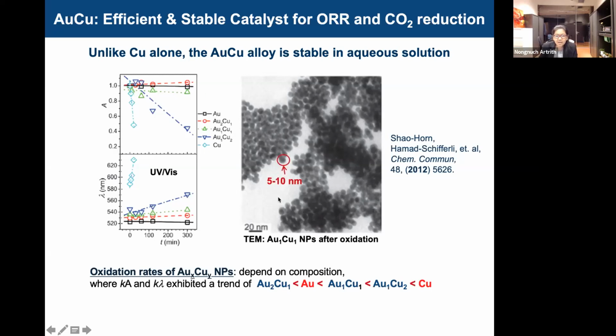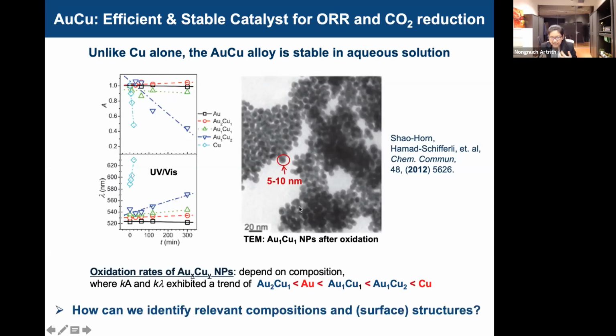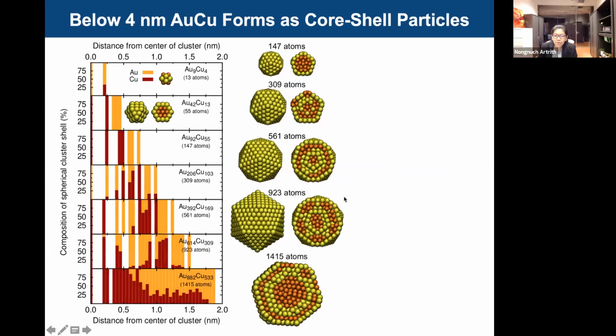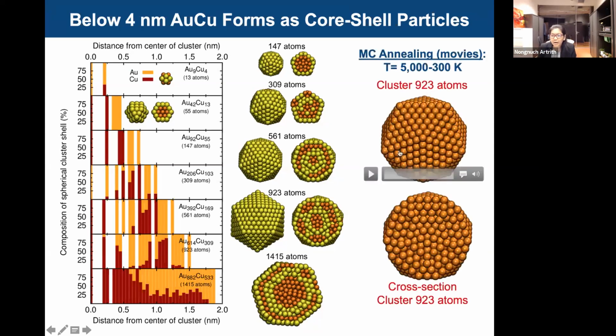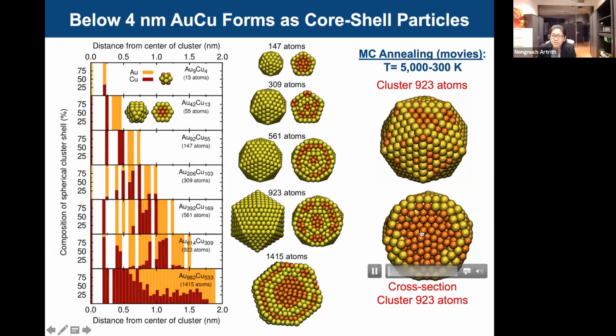But the cluster size of the system is around 5 to 10 nanometers. So as computational materials scientists, how can we help to identify the important compositions or surface structures? What we did, we again developed neural potentials for copper gold. We first looked at copper gold nanoparticles in vacuum, and then we used Monte Carlo simulations to investigate, for example, the atomic ordering of copper and gold atoms, like you can see here.